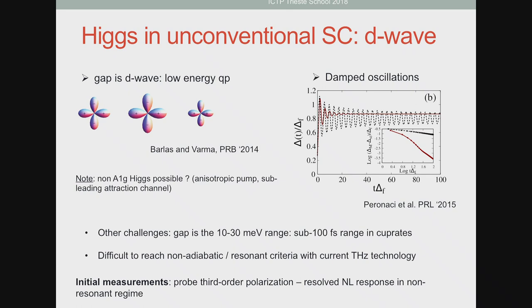So first, it's a bit more difficult to produce intense pulses in the spectral range of delta for high-TC cuprates, for example. The delta, the superconducting gap in high-TC cuprates, is several tens of milli-electronvolts, and it's a bit harder to produce intense pulses in this energy range. So in other words, the resonance condition is harder to fulfill. And of course, the equivalent of that is that in terms of reaching non-adiabaticity, it requires really ultra-short pulses, sub-100 femtosecond pulses, if you want to reach the non-adiabaticity. And this is quite challenging.